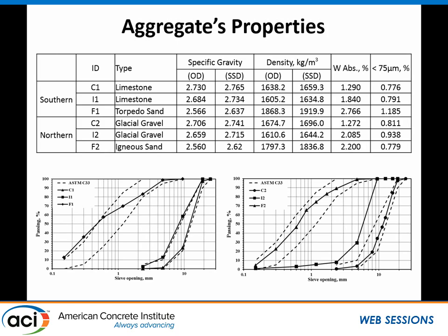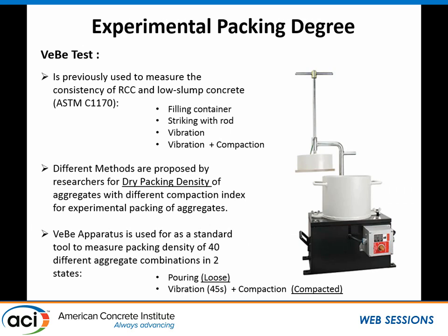So the southern aggregate is limestone. These are the properties, and then the northern aggregate. We can see that F1, the southern aggregate, is slightly finer than F2, and the intermediate for the southern aggregate is not actually intermediate. It's more towards the coarse, versus this one, which is more fine. And then there's a difference in D-max in the two of those, though they're both 1 inch.